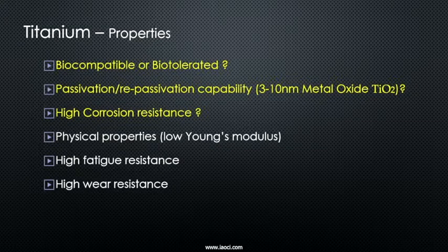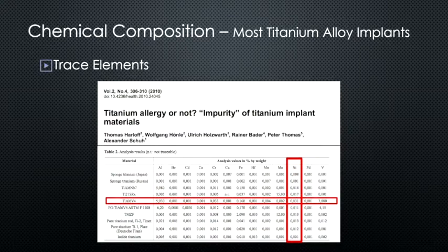So, if you look at the composition of titanium, you'll find that there's a whole host of other metals that are not mentioned in the general composition that are there, such as nickel. It's very little, but it's there. And I've had patients that have had problems with titanium implants, and when they were tested, nickel was the issue. Although minute, and I'll show you some cases.